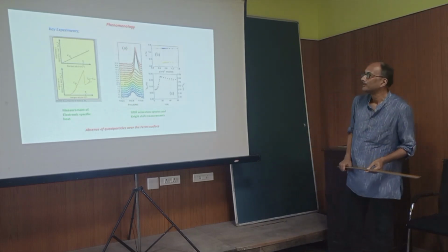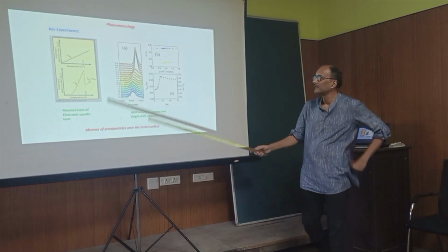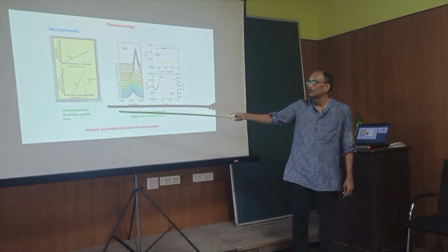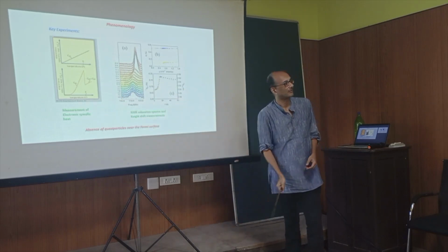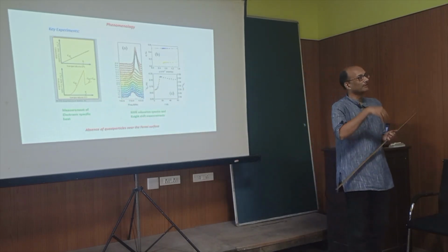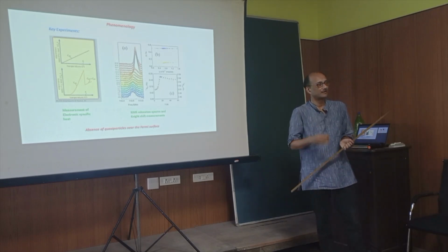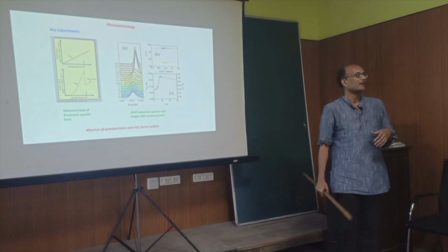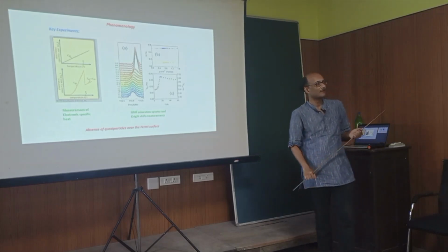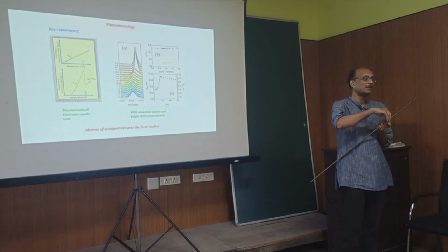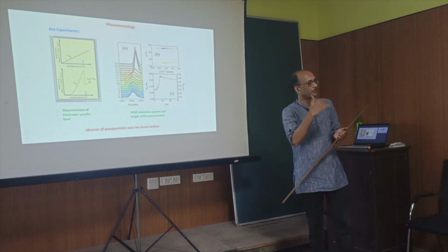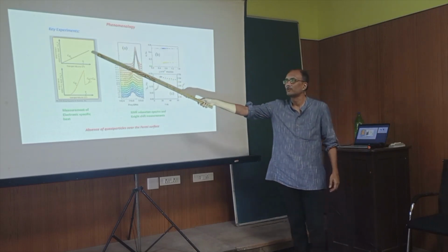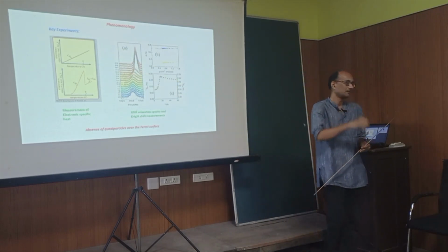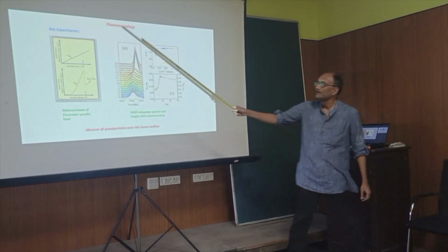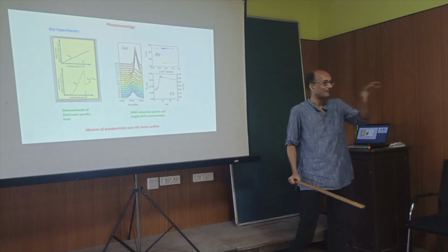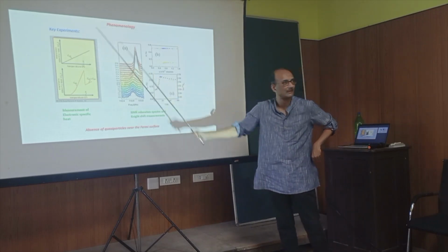So the other thing that came up, which showed why this is a different state of matter, is apparent when you measure its electronic specific heat. So those of you, when you take your first solid state courses, you will see that when you measure specific heats of any substance, there are roughly two contributions to it. One of them comes from lattice vibrations, and that at low temperature typically goes as T cubed, the cube of the temperature. And then there is the electronic contribution, which goes as linear in temperature.